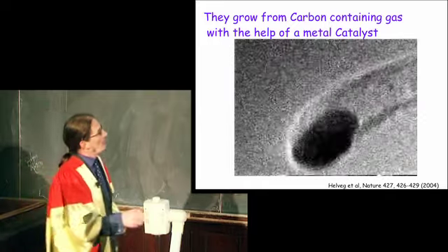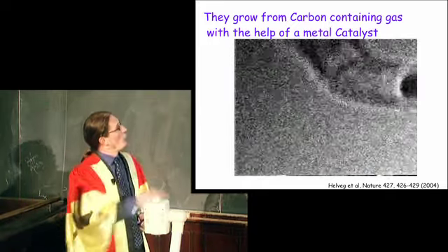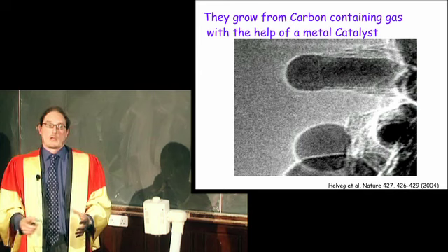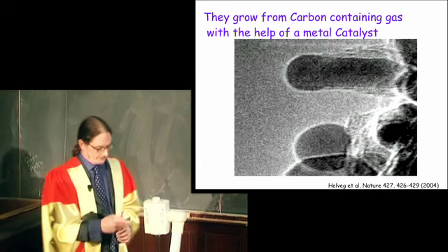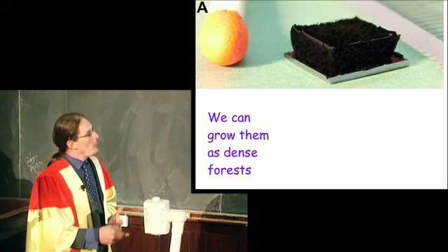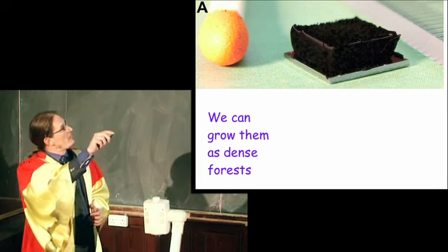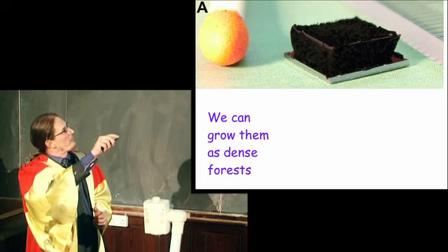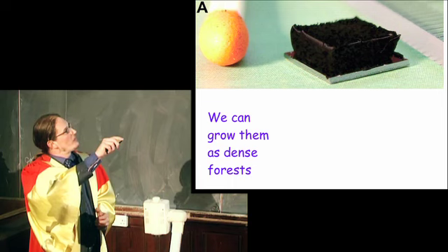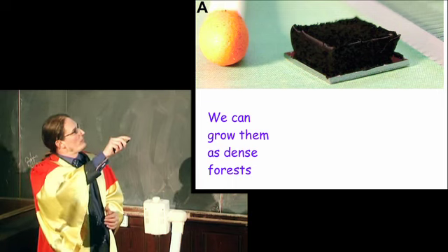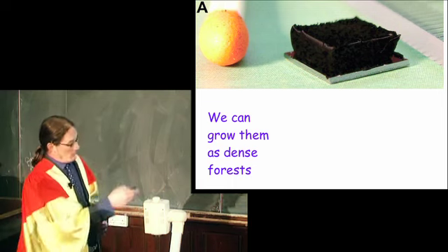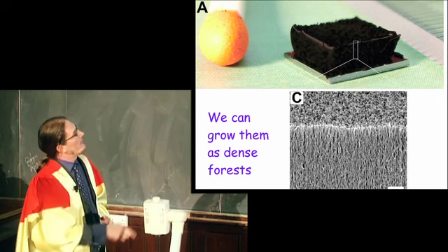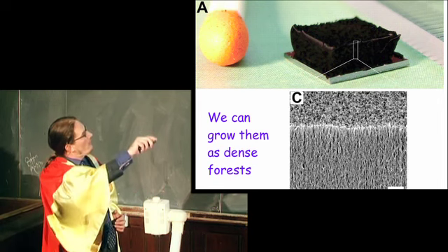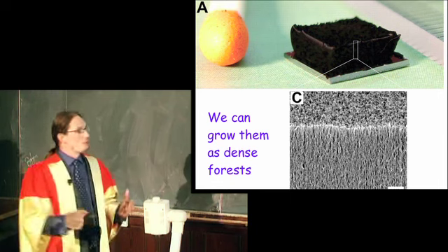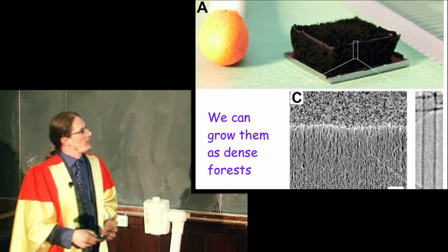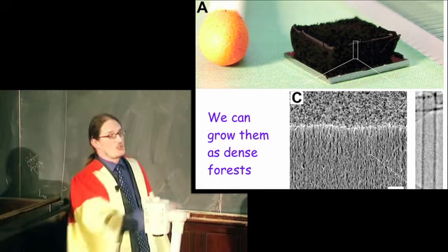Now, for carbon nanofibers, the tubes are very disordered, but if that was a single nanotube growing, it would be growing into a perfect cylinder. And nowadays, people can grow these literally by the million. This is what's known as a nanotube forest, where you've got a bunch of nanotubes growing from this surface vertically. And, well, how do I know they're nanotubes? I can look in with the electron microscope, and I see that this forest is made of an array of vertical objects, and if I look in closer, you can see that they're little tubules.